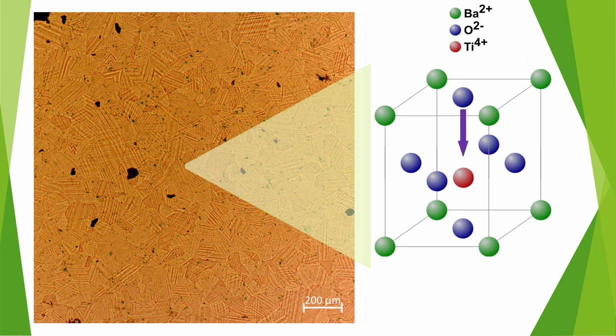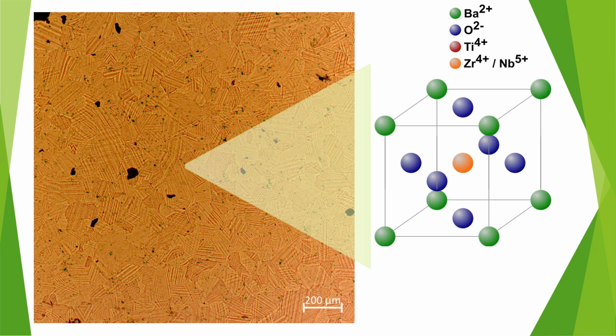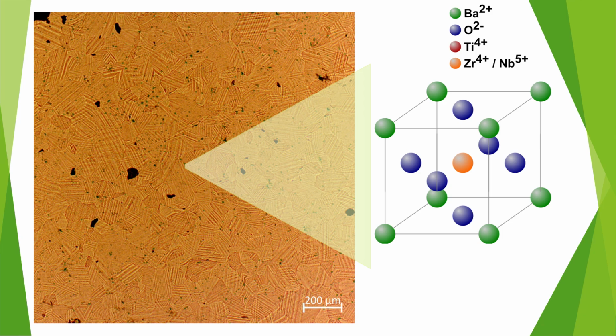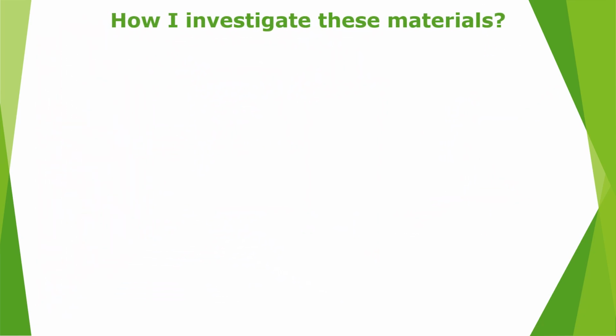To create a relaxor, this mechanism must be sufficiently suppressed, and this is achieved by replacing a part of the titanium atoms by other atoms like zirconium or niobium. These disordering atoms change the shape of the unit cell permanently, suppress the formation of domains, and ideally increase the efficiency of the system. Which brings up the question, how did I investigate these materials?